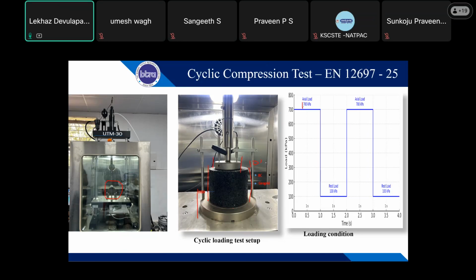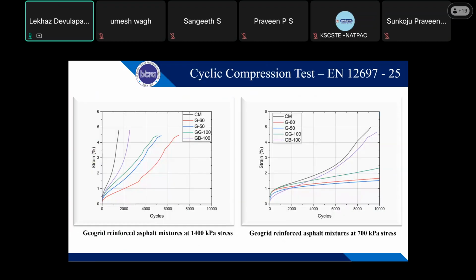We applied a 700 kPa load on the specimen for 1 second, and 1 second will be our rest period of 100 kPa, and again the loading will be applied for 1 second of 700 kPa. This is just a cyclic loading applied on the specimen, like a square loading. And we did this test at 2 different stresses. One is at 1400 kPa, which is very high, and practically that kind of load will not be there on a pavement. But still, we want to check whether the geogrids can sustain that much load. And then we did it at 700 kPa, which is a standard for our design, 560 to 700 kPa, which we consider for our pavement design as per MEPDG models.